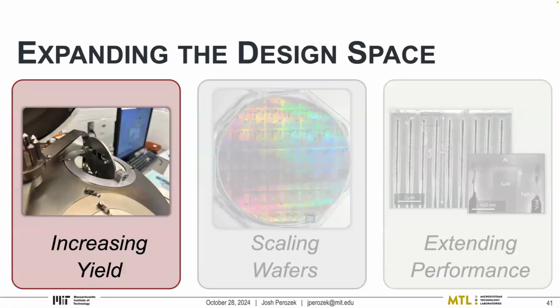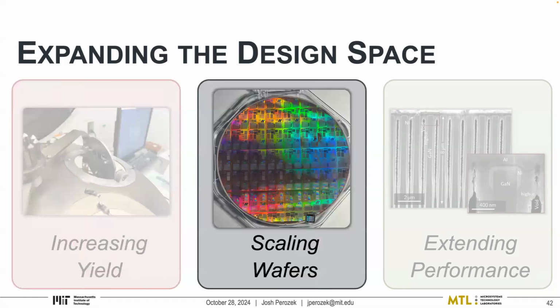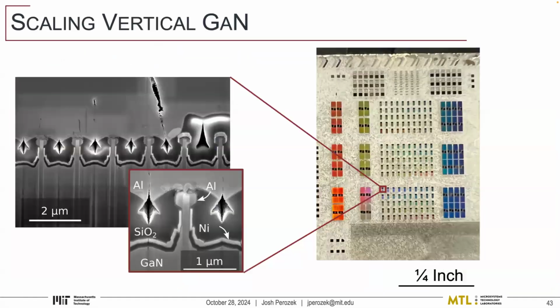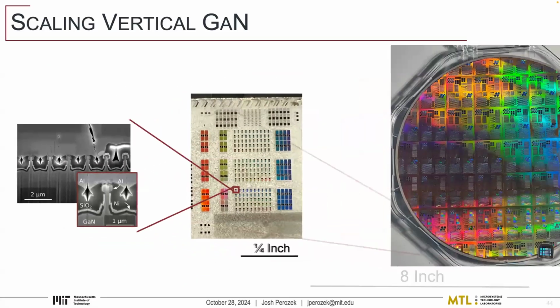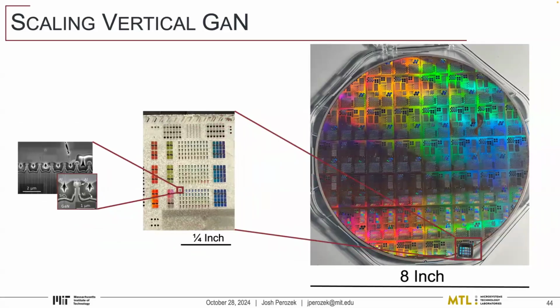So that was some of the fabrication technologies that we were able to develop to really improve the yield, the repeatability, uniformity of these devices. But we're still making them on very small pieces. And what we want to do is we want to scale to a wafer. So all the work so far has been on very small pieces of bulk gallium nitride. They're about the size of your thumbnail or a postage stamp or so. And what we want to do is bring it to an 8-inch platform. We want to make it about 200 times larger.